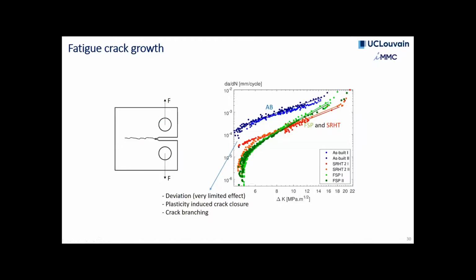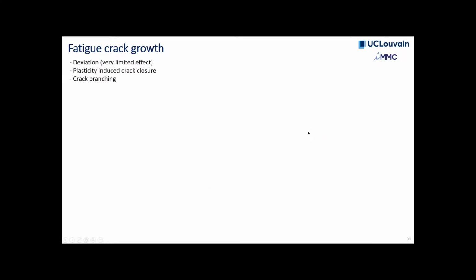And so we had a look at as-built material, friction stir processing, and stress relief heat treatment. I don't know if you guys are familiar with this, but da/dN is basically the crack growth speed, in millimeters per cycle, and here delta K is in a way the stress level. And as you can see here, the as-built material actually has a propagation of crack that is much faster than the friction stir processing and stress relief. Here in this case, friction stir processing and stress relief are together. So we wanted to make sense of that.